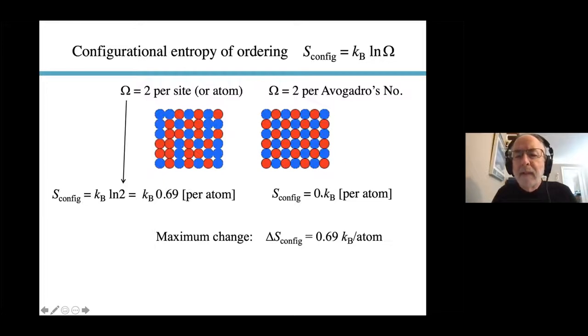Log of 1 is 0, so there is no configurational entropy when we're ordered. We go disordered and we have a random 50% chance of putting a red or blue atom here. Then we have two types of possibilities per site. Omega is 2 per atom, and the logarithm of 2 is 0.69. So the maximum change that we can get on this disorder to order transition is 0.69 kB per atom.